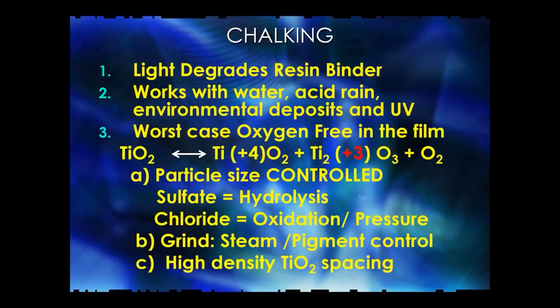So what we want to avoid in exterior applications is chalking. And what happens is the light degrades the resin binder. It works with water and acid in the environment. And in a worst case scenario, there's a raw titanium dioxide surface, and the titanium dioxide can produce free radicals which attack the resin itself. So what we do is we control the particle size first to give us the hiding power. The key to keeping the light from degrading the resin is to provide sunglasses. So we need to be able to stop it, to absorb the energy, to deflect it and move it away from the rest of the resin. So it's this catch-22: in the process of absorbing and deflecting and reflecting, we wind up degrading.